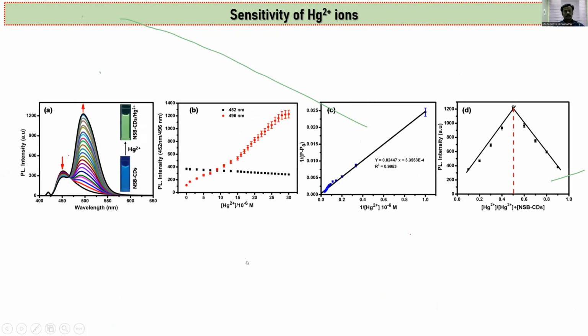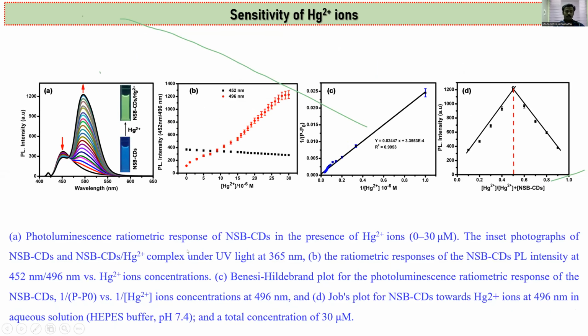Okay, the next is the sensitivity of boron doped carbon dots. Here we can see clearly at 452 nanometer, there is very low intensity, only quenching, and after different concentrations from 0 to 30 micromolar, we can get photoluminescence intensities around 1200. We can confirm from this the quenching or enhancement of intensities. We have to draw the plot. The maximum intensity appeared at 496 nanometer, and we have also calculated the complexation ratio, which we can get as 0.99.